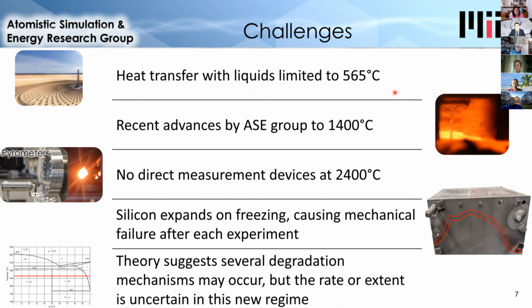For example, we can't directly measure temperature. There's really no direct contact measurement system that can be used. So instead, we just have a hole cut in the insulation of the system and we measure the radiation with a pyrometer. And so it's very hard to observe the system because of this high temperature.